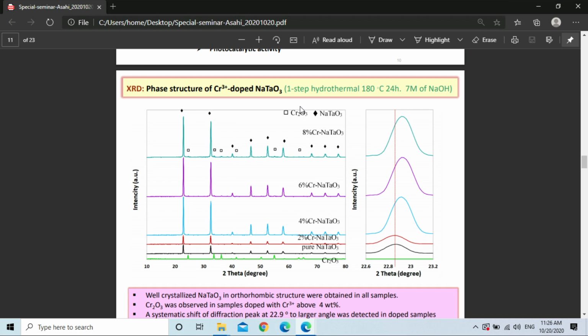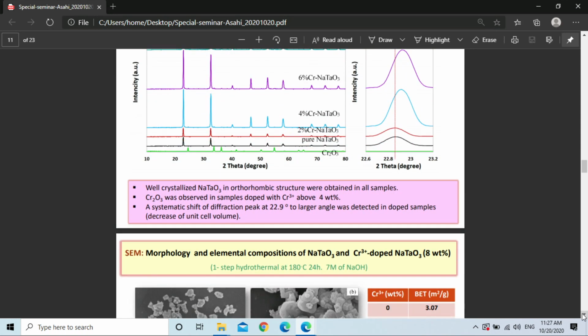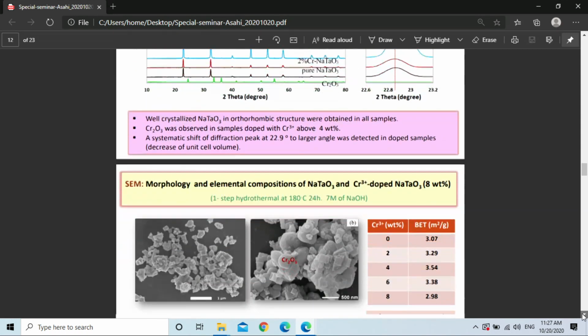And when we enlarge the peak at 22.9 degrees, we can see a systematic shift of the peak to a larger angle. It means that the unit lattice shrinks or becomes smaller because of the substitution of chromium ion, which has a smaller size than tantalum ion. This result confirms some substitution of chromium ion.